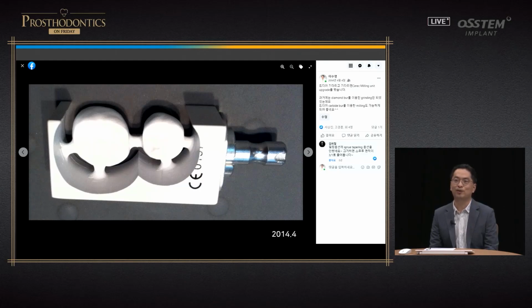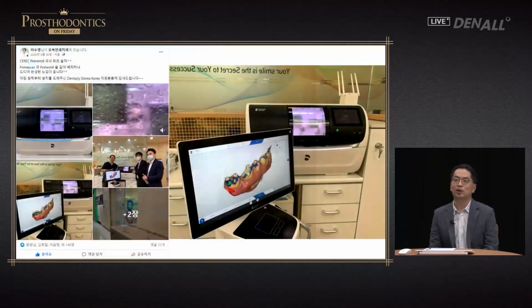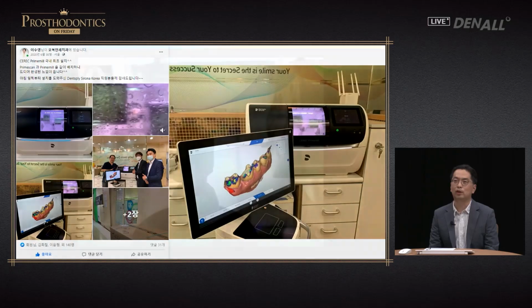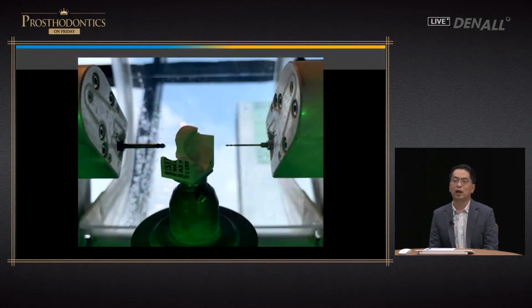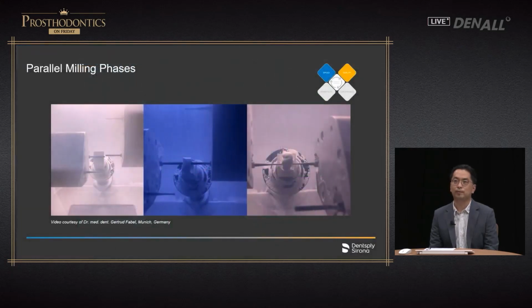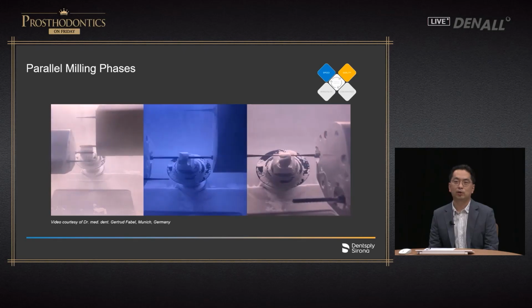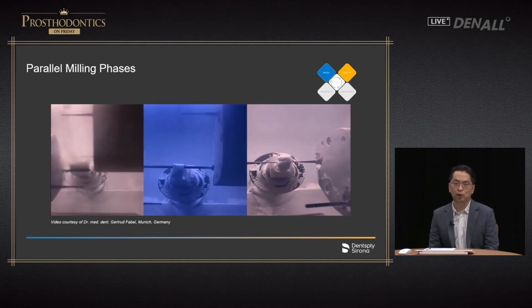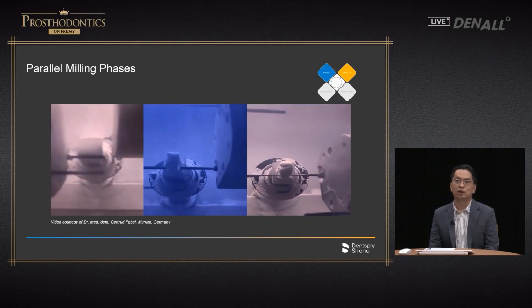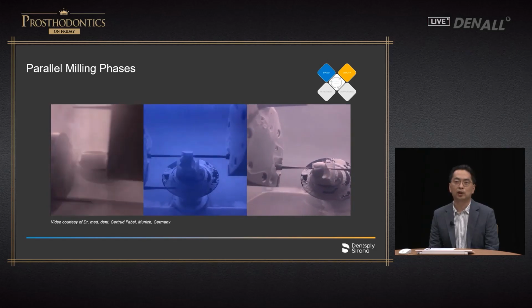The sprue size is quite significant and the level of fabrication is not really good. About 8 years ago, the level we achieved was like that, and in 2020, I adopted the CEREC Primemill. Carbide milling has significantly improved. As you can see, it's not just milled on one side, but parallel milling is now possible. On both sides, burrs are milling.